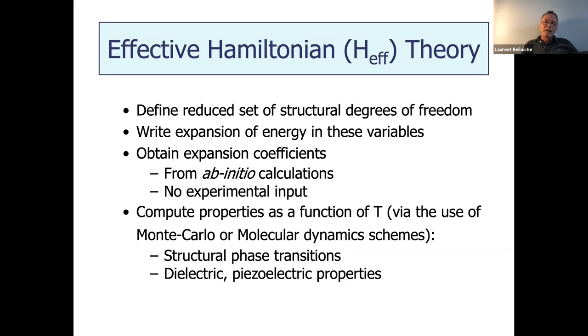It was first developed by Zhong, David Vanderbilt, and Karin Rabe in the 1990s as well. So what they suggested is that you don't look at all the degrees of freedom, you keep the most important ones. And I'm going to show you which ones are the most important. Once you have selected these, you develop an expression of the energy that depends on these degrees of freedom. And in this expression, you have expansion coefficients and you get these by doing ab initio calculations. And if possible, you don't use experimental input. So everything is at ab initio level.